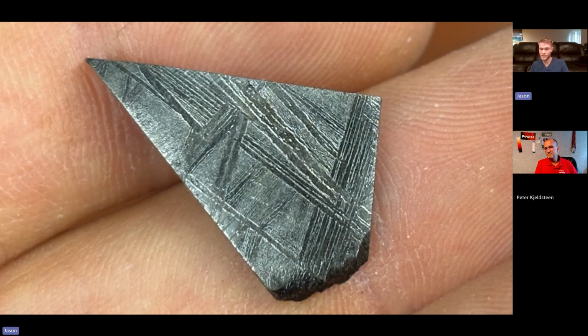Remember, taenite is a low iron phase, but at high temperatures, it can accommodate that iron. And so as we cool over millions and millions of years, that iron begins to precipitate out in a phase that is more accommodating to iron. That is kamacite. Kamacite is a higher iron phase. And so as we cool down, kamacite begins to precipitate to relieve the stress on the taenite. And because we're cooling so slowly, that kamacite, which are these rods, can grow in preferential growth directions. When we cool very slowly, we get very nice facets of kamacite. We get a very pristine structure. And so they begin to grow in these very long rods in preferential growth directions. And that's why we see that these kamacite rods always intersect at very specific angles.